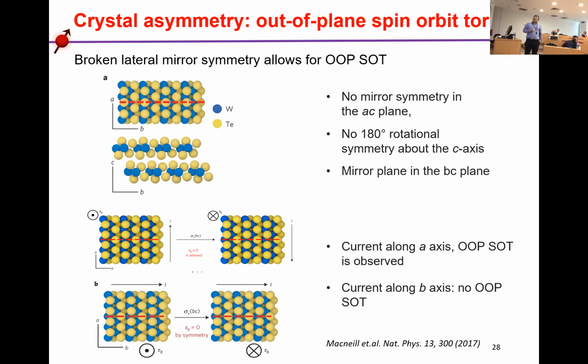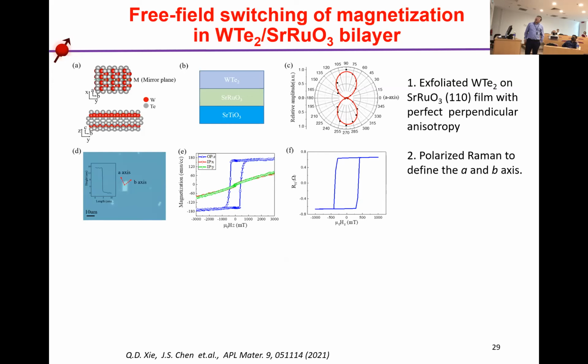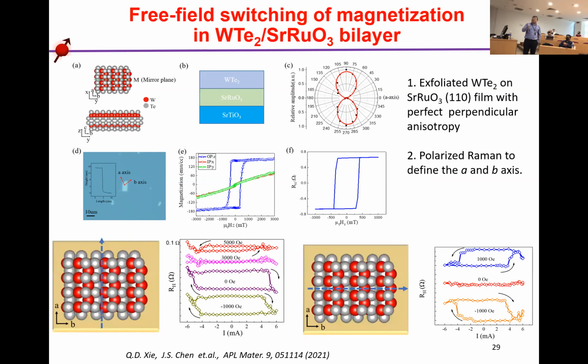of the magnetization. In my group, we have also done this. We use strontium ruthenium oxide as a ferromagnetic material. From here, we can see it shows perfect perpendicular anisotropy. And we put exfoliated tungsten ditelluride on top of this strontium ruthenium oxide. And we use polarized Raman to define the A-axis and B-axis. And then we make the device. Actually, we have demonstrated that when the current is perpendicular to the mirror plane, it causes zero-field switching, field-free switching. And when the current is parallel to the mirror plane, there is no field-free switching.